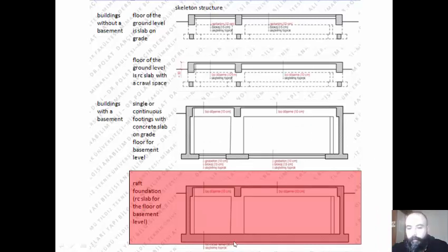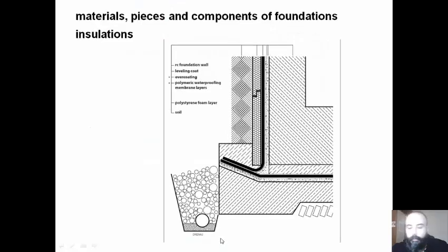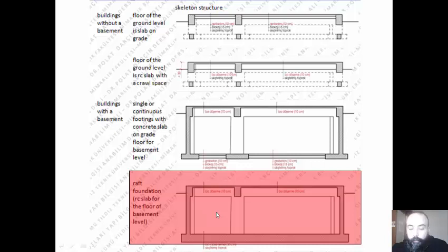And for this type of foundation, where the water table is higher than the footing level, we used a reinforced concrete raft slab, and we cannot prefer waterproofing admixture here, because even if we put the waterproofing admixture and made all these reinforced concrete components waterproof, there could be some settlement or small earthquakes which causes some cracks through these shear walls or raft slab, and even if the components are waterproof, there can be water leakage through these cracks because the water table is way higher than the footing level, and there is this water pressure.